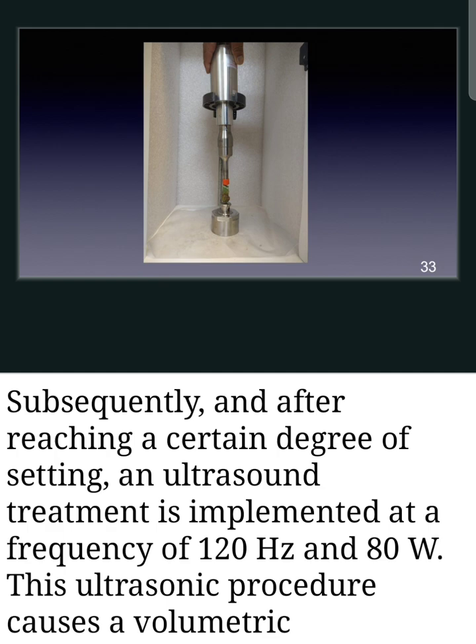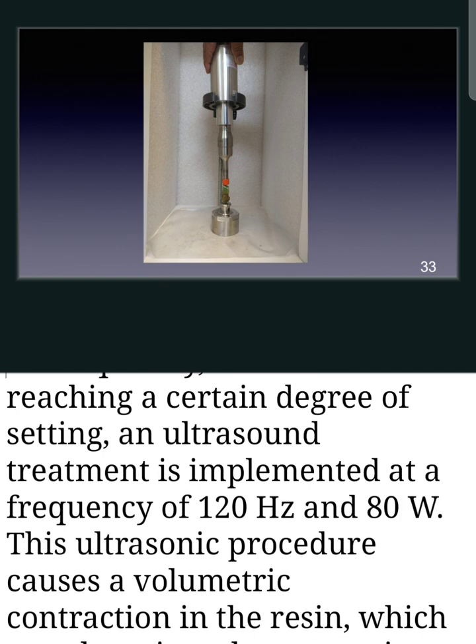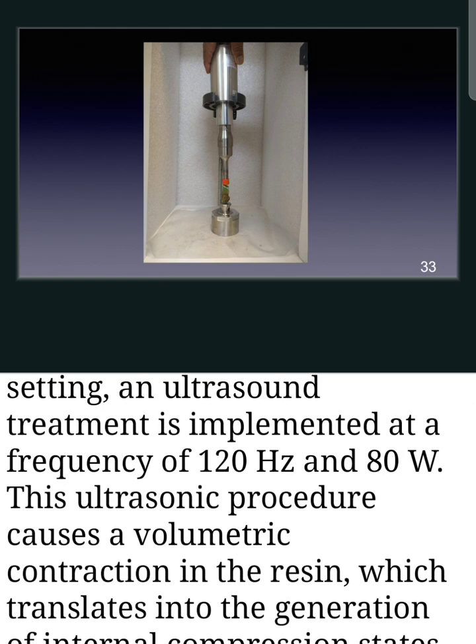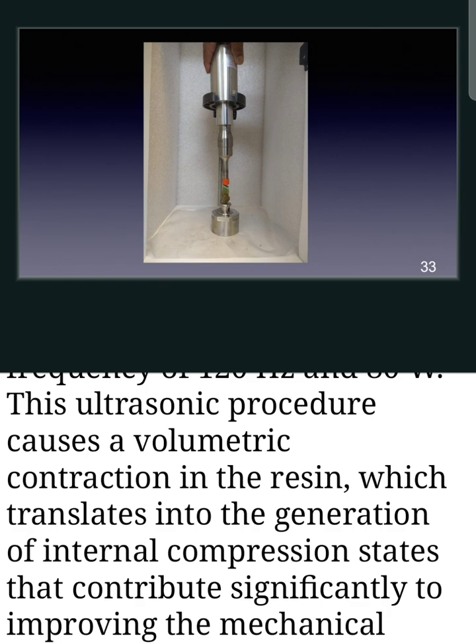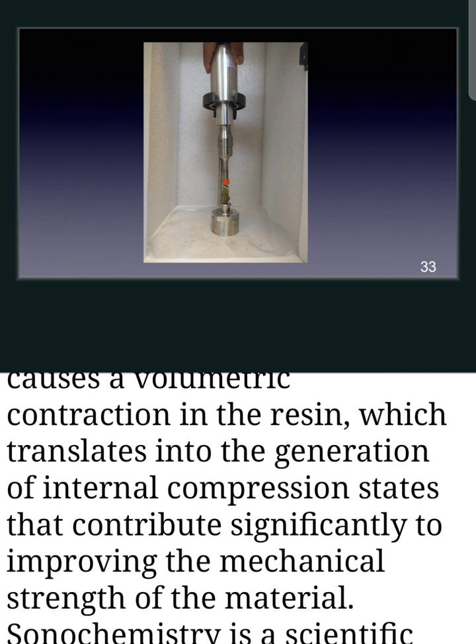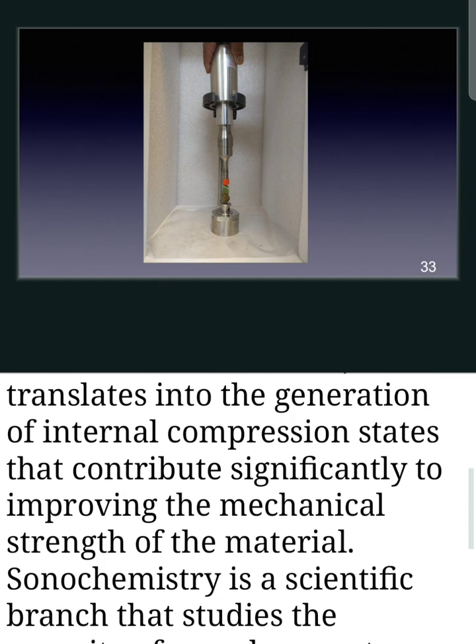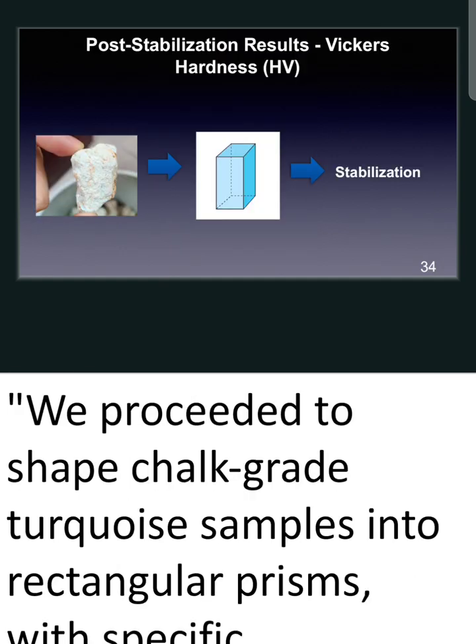Subsequently, and after reaching a certain degree of setting, an ultrasound treatment is implemented at a frequency of 120 Hz and 80 watts. This ultrasonic procedure causes a volumetric contraction in the resin, which translates into a generation of internal compression states that contribute significantly to improving the mechanical strength of the material. Every sample we talk about now was treated by this stabilization method.